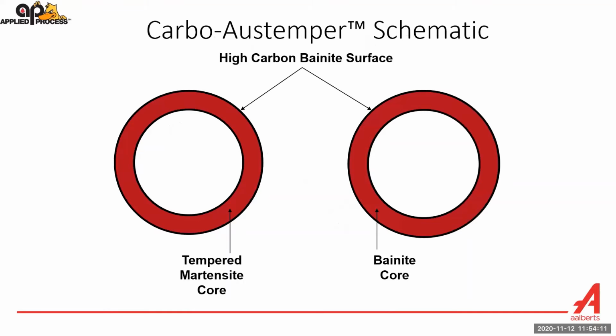I had mentioned another process that's called Carbo-Austempering. So in the furnace, we can process the parts at temperature and have a high carbon potential in the atmosphere. And what the carbon then does is it works its way into the steel over time. So imagine this was 4140 steel and it was carburized. Instead of being 4140 on the surface, it might be 4180 steel, so it's got a higher carbon content. So you can get a harder surface and a softer core. You can have good wear properties, but good toughness because of the softer core of the material. This almost is a composite material.